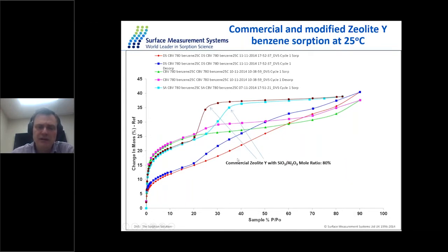But by modifying the chemistry of these materials, I can change the porosity. So what I can see, I still get quite lots of microporosity, but I can completely change the isotherm. So from a typical type 1 isotherm, you can go to a type 4 isotherm with a huge hysteresis, showing that benzene is not actually coming off during the desorption. So by changing the chemistry of the materials, I can actually change the isotherm. So the other way to look at this material.